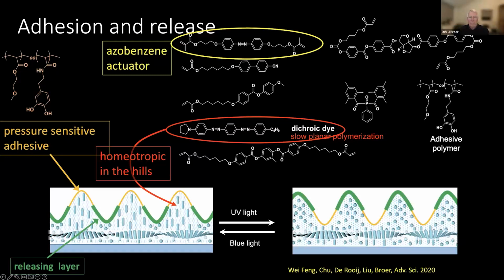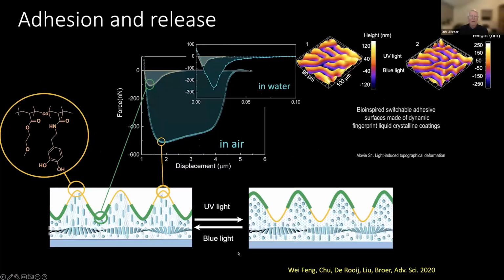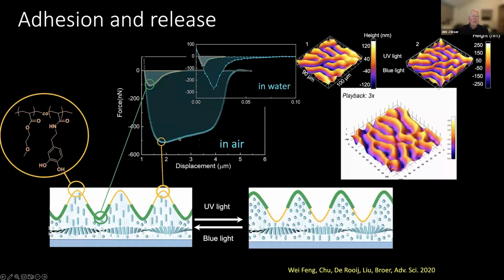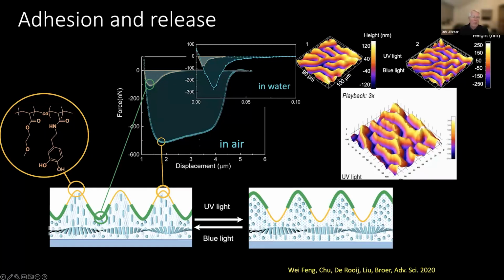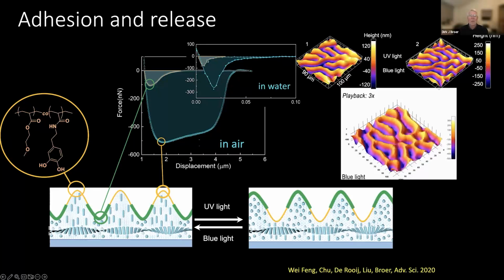And then by inverting the structure, we could bring a releasing layer at the other side. And now we can switch between an adhesive state and a releasing state just by either exposing with UV light or by exposing with blue light. And in this case, we can go from a highly adhesive state to a low adhesive state when these areas come up. Or even in water, again, we are using this mussel type of protein, it works also very nicely in water, from a highly adhesive state to a low adhesive state.